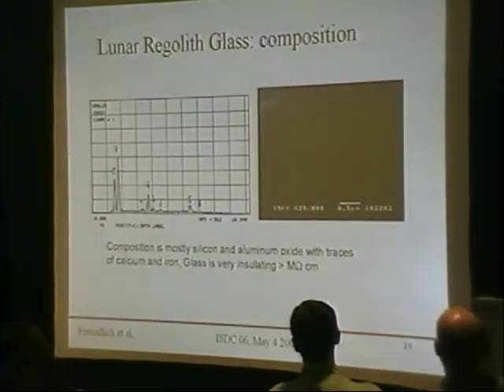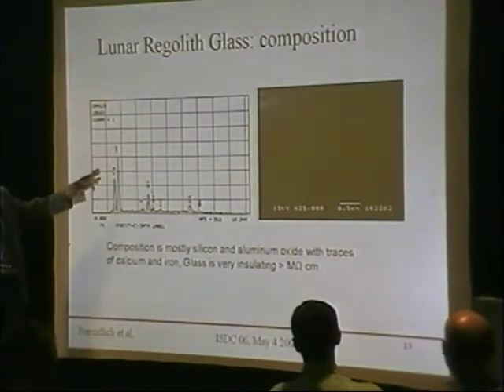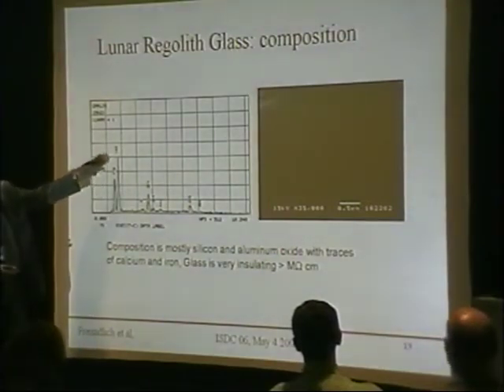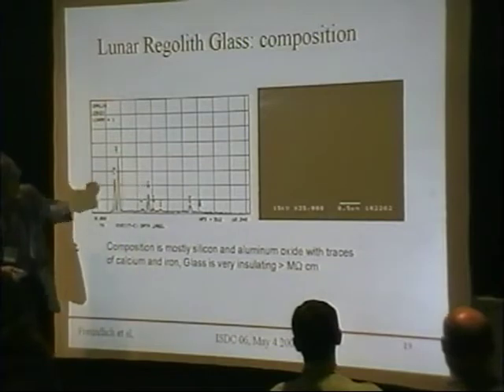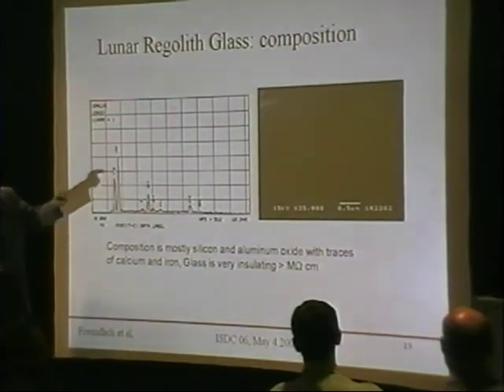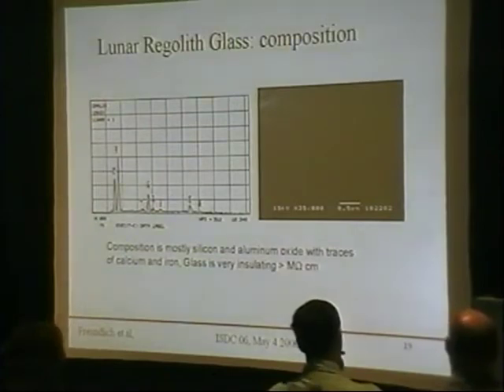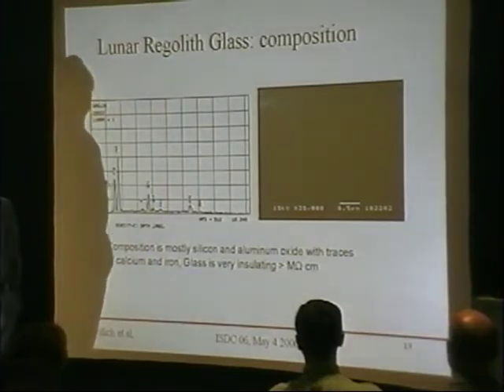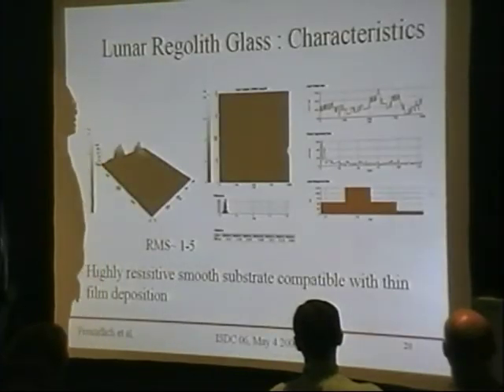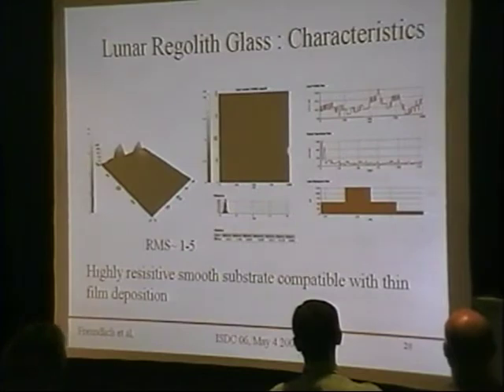The composition of the glass obtained is mainly aluminum silicate with some content of calcium and a small amount of iron. The resistivity of this glass we couldn't measure. It was so high, in the high megohms. Next.